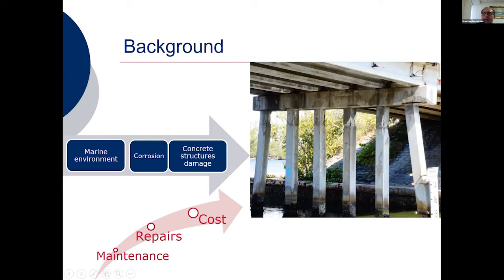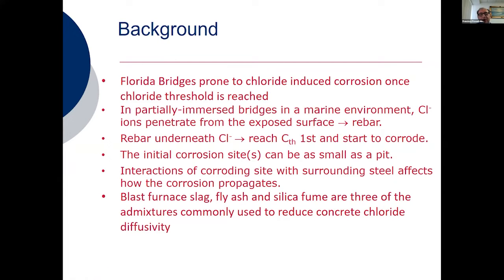When you expose reinforced concrete structures to marine environments, like here in Florida, they might be prone to corrosion once the chloride threshold has been exceeded at the rebar interface. In the type of structure that I showed you a moment ago, the chlorides penetrate from one surface and go towards the rebar. There is a geometric effect in some cases. But at the location where you exceed the chloride threshold, there might be some defects at the interface that make it the location where corrosion starts. The size can be very small, like a small pit in some cases. Then interactions with the surrounding reinforcement might determine how that corrosion propagates. Some people say there is going to be a halo effect and some cathodic prevention due to the side that is corroding.